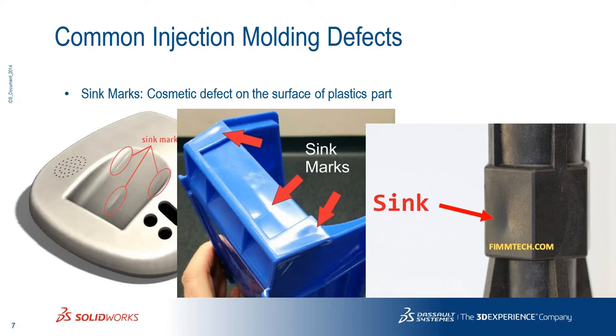Sink marks occur when you have non-uniform thickness in the material. When reaching areas with variation in thickness — a thicker area — after the shrinkage of the material you will find some dips on your part. We define these as sink marks. It's a cosmetic defect visible on the surface of the plastic part, and you can see them clearly in plastic parts that have deviation and difference in thickness.